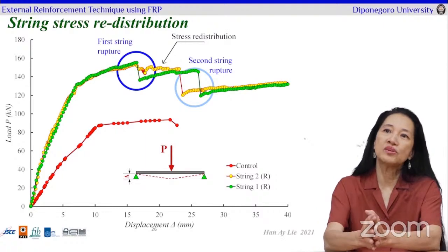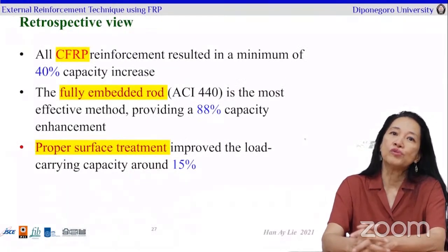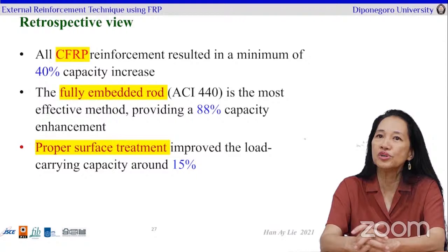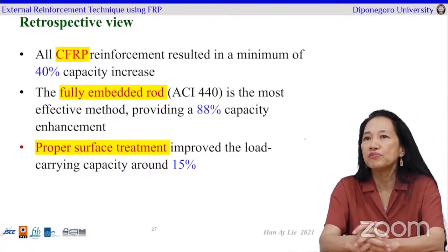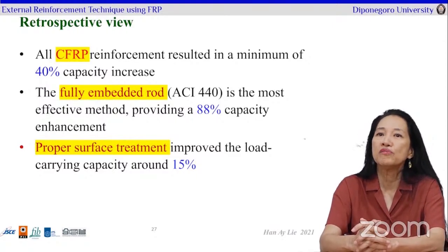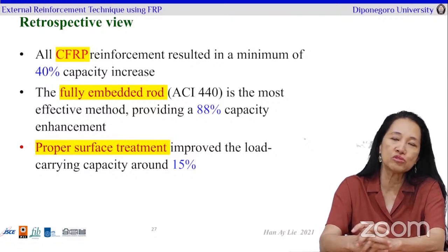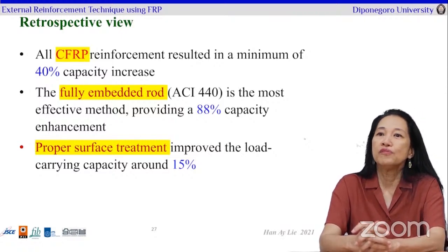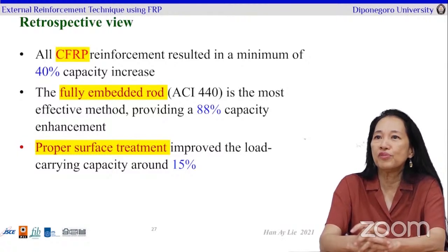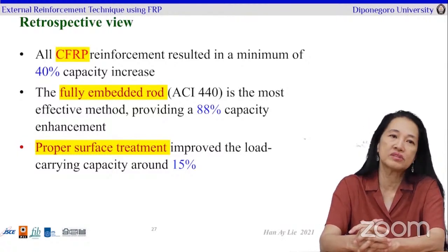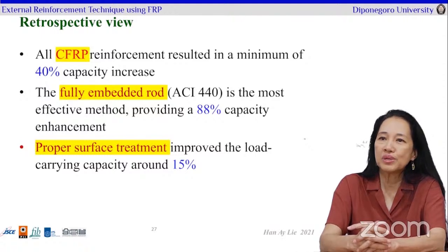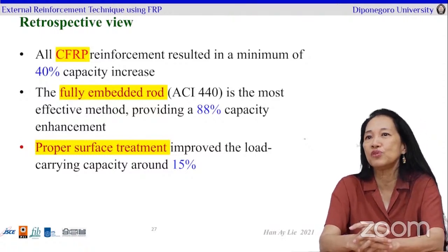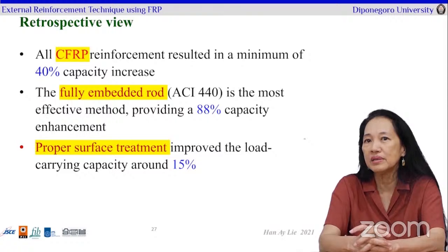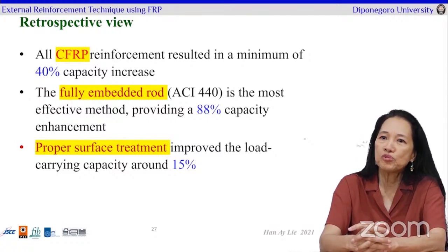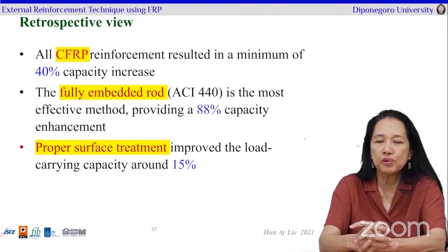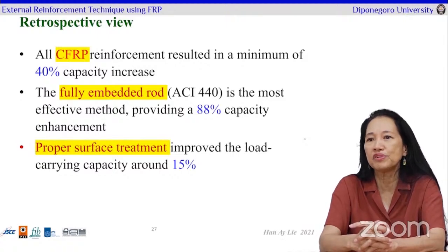So now let's look at the remarks. What can I tell you from our 4-5-year research? All the CFRP reinforcement resulted in a minimum 40% increase in capacity, so it's good. The full embedded rod, according to the ACI 440, is the best. It almost increased the capacity twice if you compare it to the control element. And also, proper surface treatment will improve the load carrying capacity around 15%.